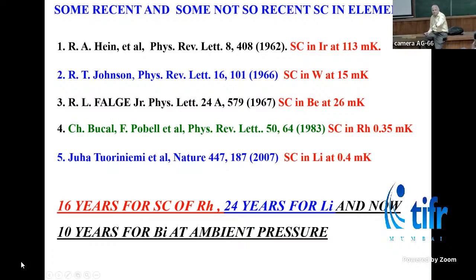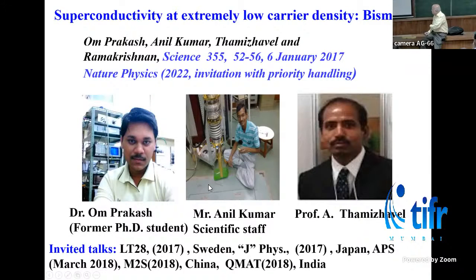It's extremely reactive. So for that, they have to make a crystal, seal it, and then put the sealed one in thermal contact with the system. It's a mind-boggling experiment. No sane person will do it, but the Helsinki group are not sane people. So they did it and showed it, and it became a big splash in Nature. So after 16 years for rhodium, 24 years, then we showed that bismuth can superconduct. So this has an interesting history. I built the dilution fridge, the microkelvin fridge, with another student, Naren, who couldn't reap the benefit. He set it up. By the time he set it up, his time was up.